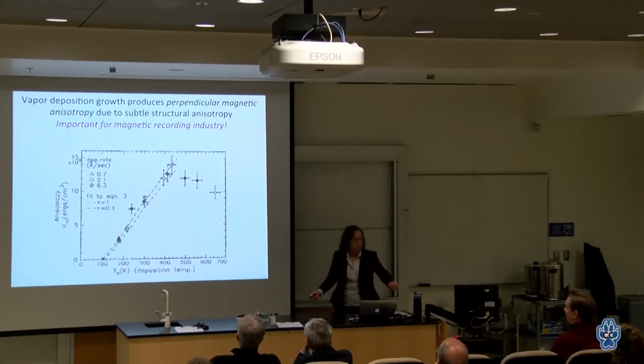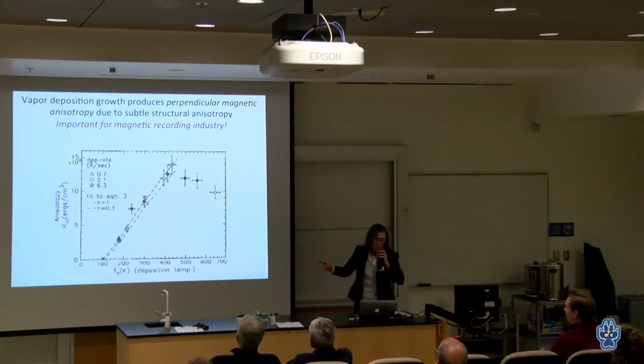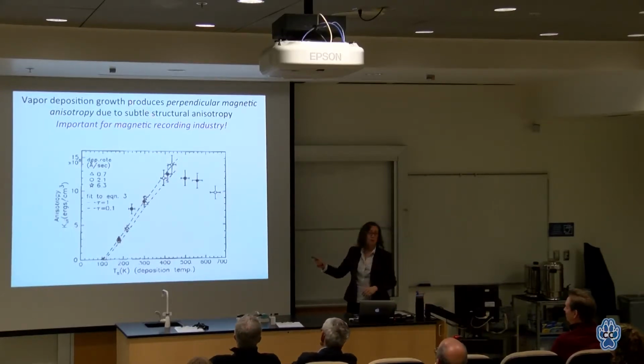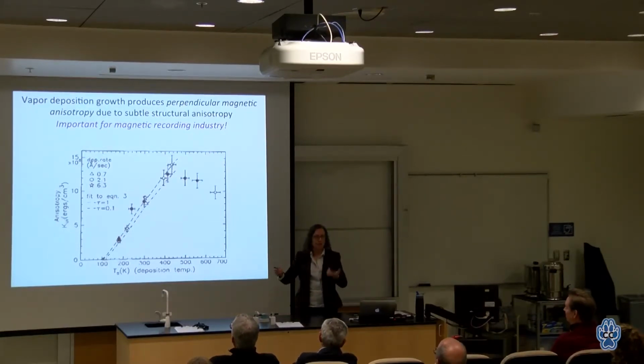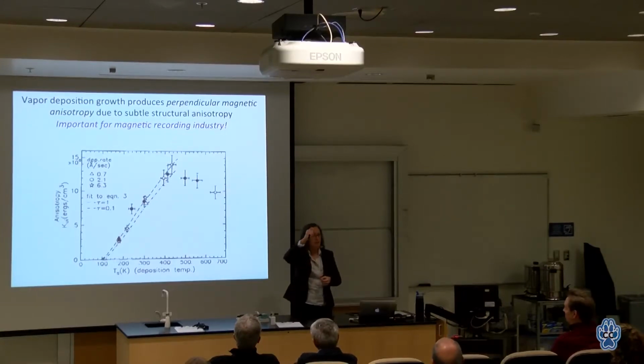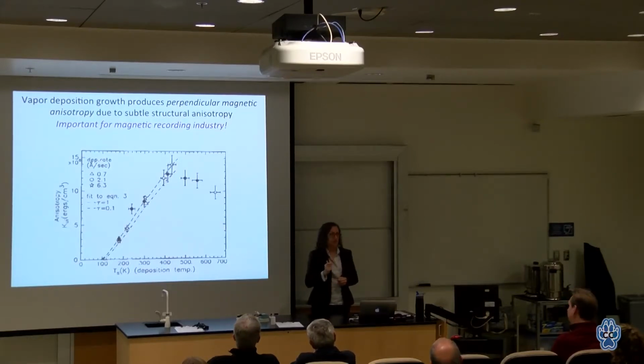And it turns out that amorphous terbium iron and its perpendicular magnetic anisotropy makes it quite important for the magnetic recording industry. So this rather obscure effect, and by the way, the fact that it is magnetically anisotropic means it must be structurally anisotropic. We believe it's because there's more terbium iron pairs out of the plane and more iron iron pairs in the plane. But it is a very subtle structural anisotropy.